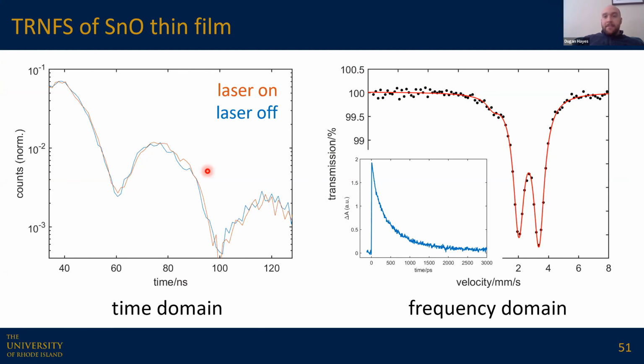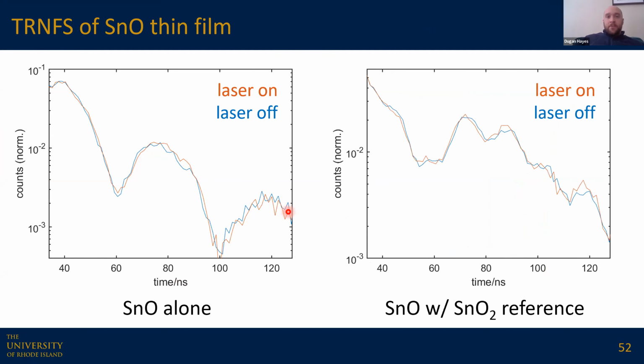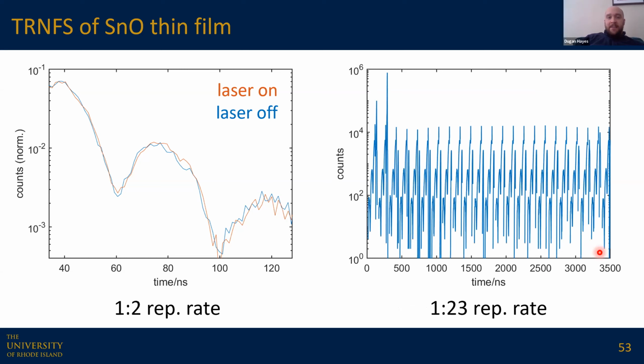And so here's what we get. This is our steady state spectrum of a tin 2 oxide thin film. We get a laser on and laser off spectrum. We can measure it with a tin 4 reference, so we get this quantum beating that will get us back our isomer shift relative to that.